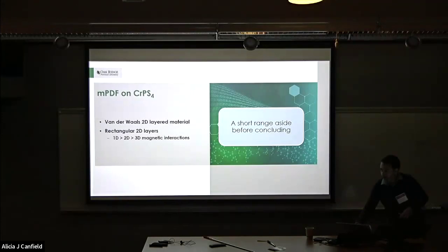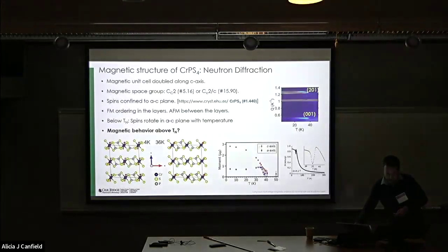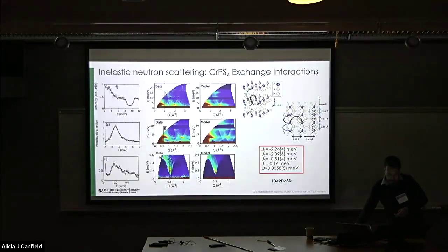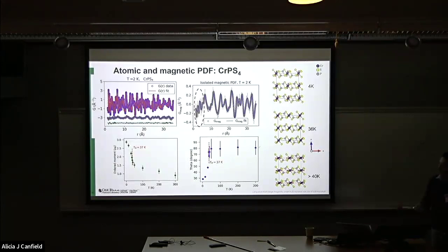Okay, so that was the end of that part. I think Chris is standing up, so I will skip through this and show just one plot here. This is the last slide, I promise, where we looked at the MPDF. This is just a motivating line where you get a lot of information from MPDF in CrPS4, a different van der Waals material, where we were able to look at the spin ordering through the transition. We could see that in the paramagnetic phase we get a different spin direction than when we go into the ordered phase. This is something that MPDF is very well suited to doing. You can get information on correlation length and moments, and also look at different ordering in the so-called paramagnetic short-range ordered phase and the long-range ordered state.